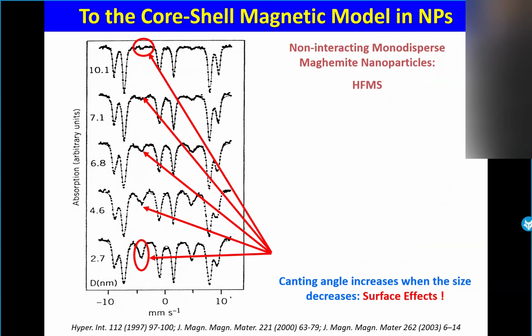So now you consider nanoparticles of different sizes. The diameter is given on the left side, so you can see from 2.7 up to 10 nanometers. These were prepared by Jean-Pierre Jolivet, as Davide mentioned this morning. He was a chemist. After we made some experiments, such nanoparticles were far enough apart to prevent any interaction in between. So they are free.